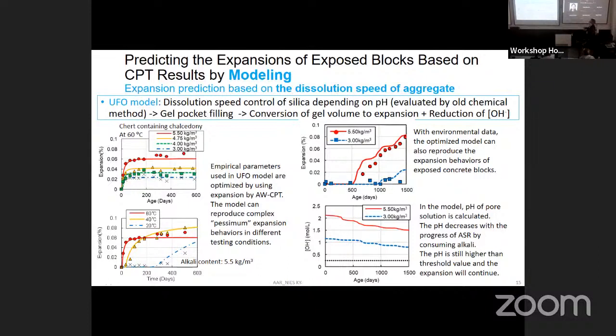We applied this model to some field exposure block. Then good correlation was obtained because, of course, in this case, temperature variation day to day was considered in the model. Simultaneously, we can calculate the alkali concentration in pore solution. So there should be a threshold value for alkali-silica reaction. According to this value, there is still a higher value than the threshold value, so expansion will continue.